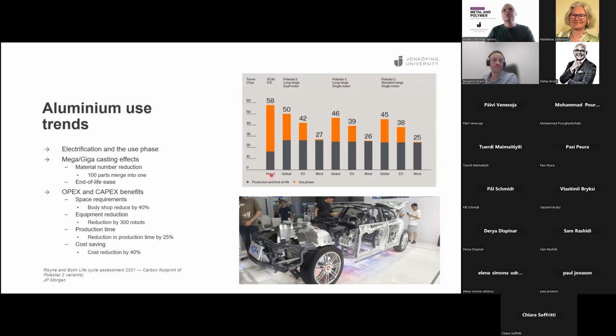And then if we go to electrical vehicles, you have an increase in the material usage. So this is essentially the battery, a little bit also on other material usage. And then the better energy mix you have, the better the overall footprint is. So with a completely green solution, we have about 50% reduction of the actual greenhouse gas emissions, of the carbon equivalent footprint. But this portion here, as Benjamin said, depends a little bit on your material reduction sources.